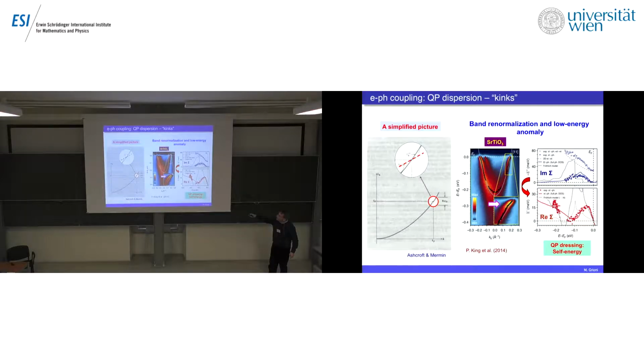electrons. If one knows the dispersion of the band without the electron-phonon coupling, then one can determine the shift which forms this kink, and therefore the real part of the self-energy, or one can determine directly from the broadening of the spectra the imaginary part of the self-energy. Anyway, the two have to be consistent. They're, of course, related by Kramers-Kronig. And then, therefore, one can characterize fully the interaction.